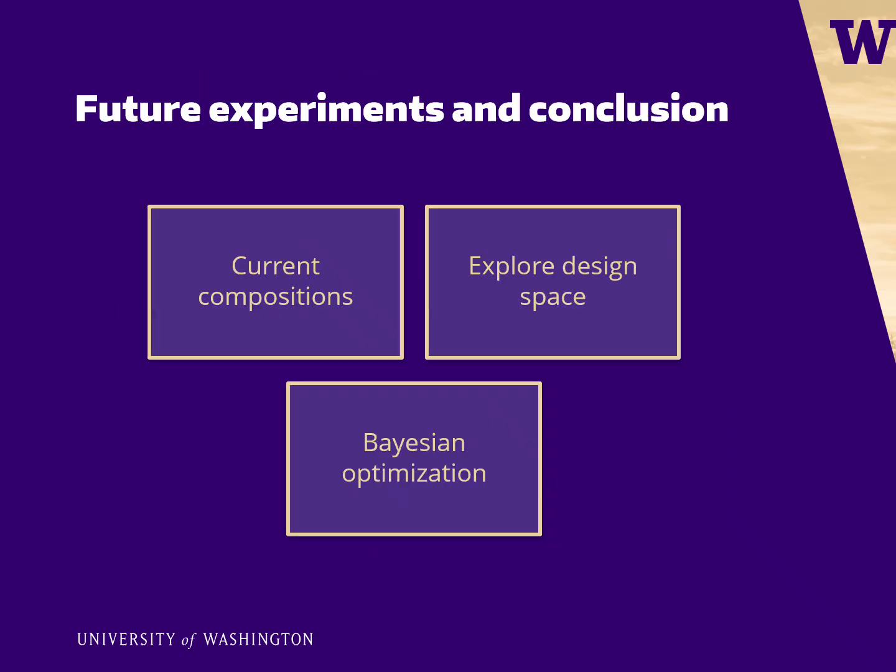Seeing how an increase in vanadium increases the alloy's resistance to volume changes in higher temperatures, and how increasing zirconium makes the alloy stiffer, it opens the door to exploring the compositional design space. In future experiments, the database of material properties and compositions that were made can be fed into a code that will predict new HEA compositions to optimize all the material properties.